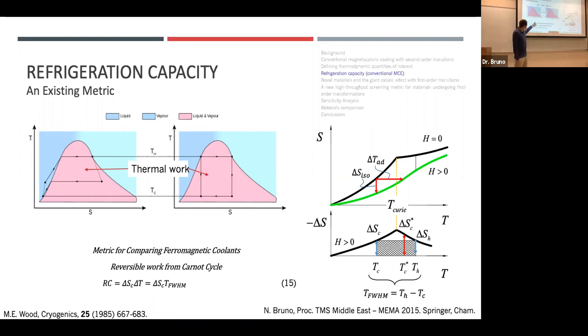All right, so the reversible work they found from a Carnot cycle is refrigeration capacity, and that was the isothermal entropy change that was achievable at some cold temperature reservoir, multiplied by what they didn't know, right? What temperature range should we apply this thermal cycle? So they used full width half maximum of the entropy change curve. Kind of ambiguous, like, okay. But if they did it for all the different materials, they could use it as a comparison between what material would give us the best response.